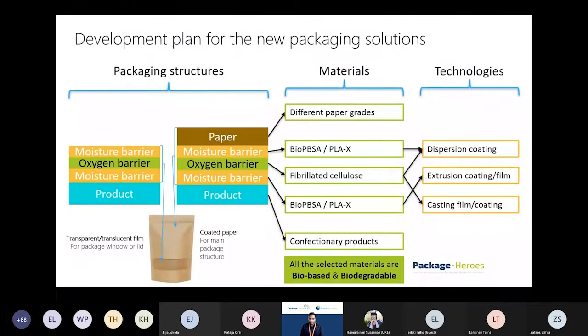And this is a brief slide highlighting our development plan for these materials. And if we look at the left side, where we have these packaging structures, we had two types. One packaging structure had a moisture barrier layer, oxygen barrier layer, and another moisture barrier layer. And this was a transparent or a translucent film, which was used as a package window or a lid. This package design that you see here, this is just for showing you where these different parts were used. We did not actually make this type of package.